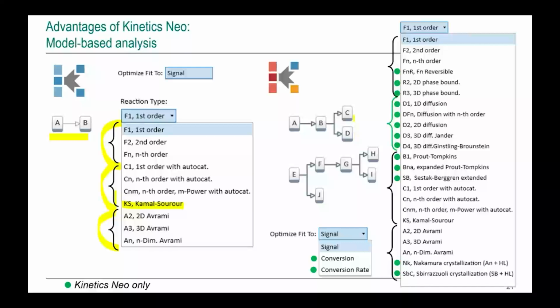Kinetics Neo has complex reactions where we have several reaction steps, and there is any combination of them. It could be competing, it could be parallel, it could be one after another, consecutive. The optimization of the model could be done not only for signal, but for conversion rate as well. We have additionally a reversible reaction and phase boundary reaction. We have a group of diffusion reactions.